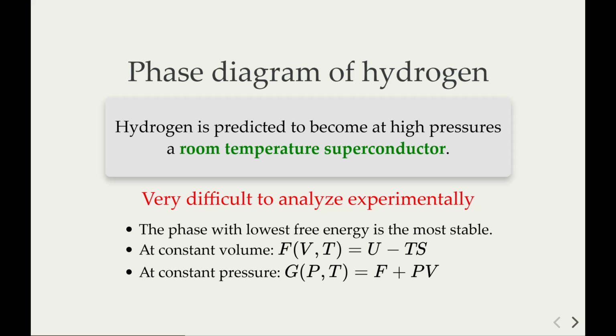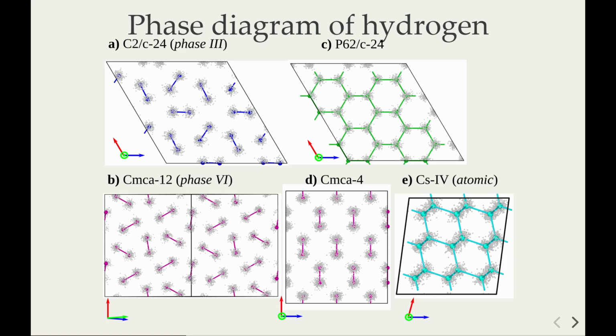So we need theoretical simulation in this case to shed light on what are the possible phases, the possible structure candidates, and then compare them with the experimental data we have to see if we guess correctly. Now, to compute the phase diagram theoretically means to find the phase that minimizes, since we are at high pressure and constant pressure, the Gibbs free energy, which is the Helmholtz free energy plus pressure times volume.